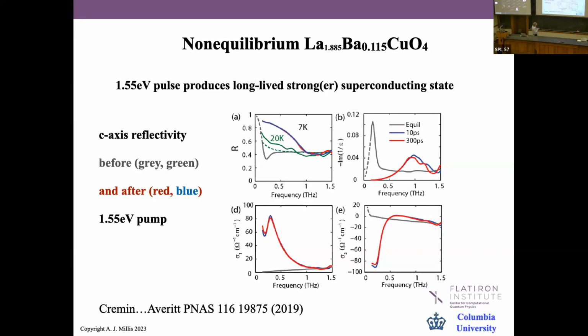And here is red and blue superimposed after—so you see the reflectivity is higher. They've converted the reflectivity into conductivity, and you see that basically what you get, especially for the dissipative or reactive part of the conductivity, is this large negative thing, which is characteristic of superconductivity. That's the reactive response that tells you that you have superfluid carriers.